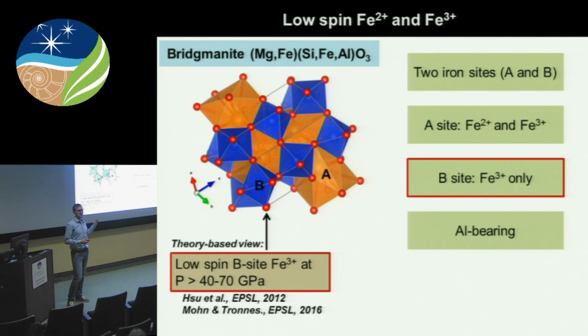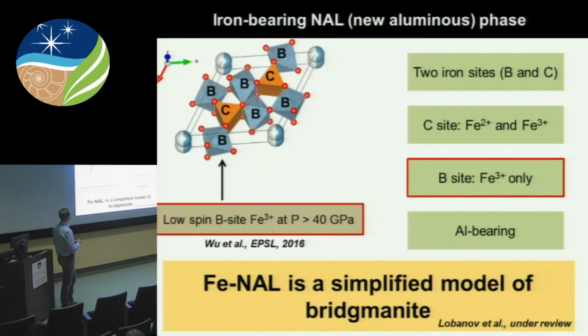However, there is a theory-based view that it is only the Fe3+ iron at the octahedral site that undergoes a spin transition at approximately 40 to 70 GPa. So what I want to say here is that this theory-based view actually provides us with a very nice testable hypothesis to set up our experiments. But before we do that, we should know what are the optical signatures of low spin Fe3+. And to do that, we looked at other minerals that have Fe3+ iron at an octahedral site that undergoes a spin transition.